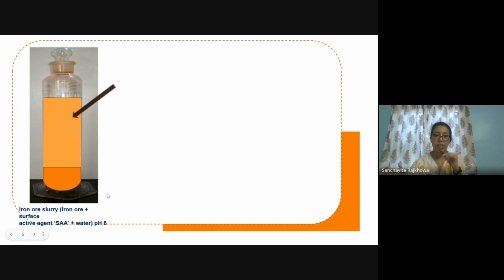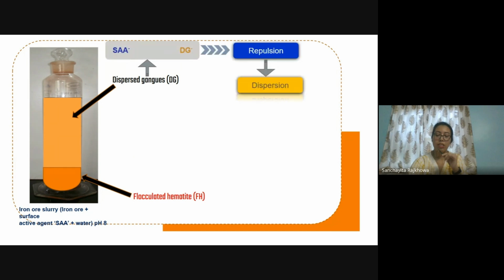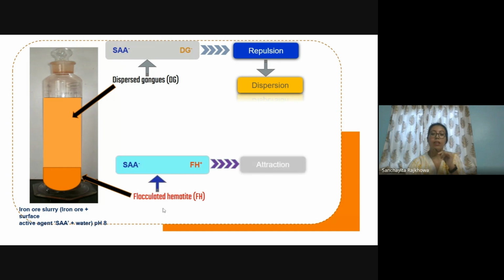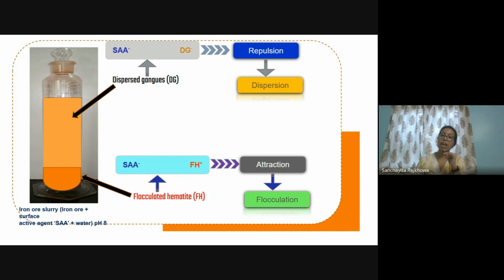Now, these are the different sections of the iron slurry, you can say. The upper portion is the dispersed gangue, and the lower portion is flocculated hematite. And this gangue suspension is also studied using different surfactants, surface active agents. While this surface active agent is anionic, this dispersed phase is also negatively charged because of the pH 8, so there will be repulsion and dispersion will occur. However, in the flocculated section, the interaction between the surface active agent and this portion will be attractive because of their opposite charges, and flocculation will occur.